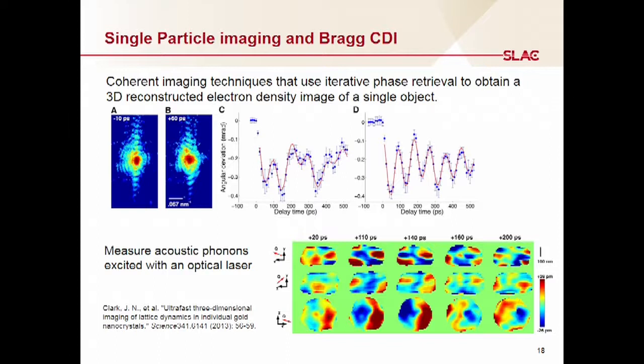An experiment which they did here at XPP, but which can probably be done at XCS or maybe even MFX, is that they took this nanoparticle and hit it with an optical pulse. What they were able to do is excite an acoustic phonon mode. And they could do a reconstruction of the particle at all of these different time delays, and see how the strain and the beating of the acoustic phonon mode exists within this particle.